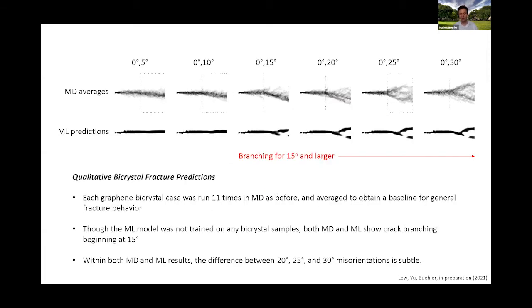And we can look at design suggestions again. We can look at grain boundaries between different microstructures and understand how branching happens. And branching, of course, you remember the composite example earlier, we want to have branching so that the crack doesn't just go straight. We want the crack to go in many different directional changes, so we have tortuosity of the crack, which leads to high fracture toughness. So this is a design objective that we can now implement very efficiently.